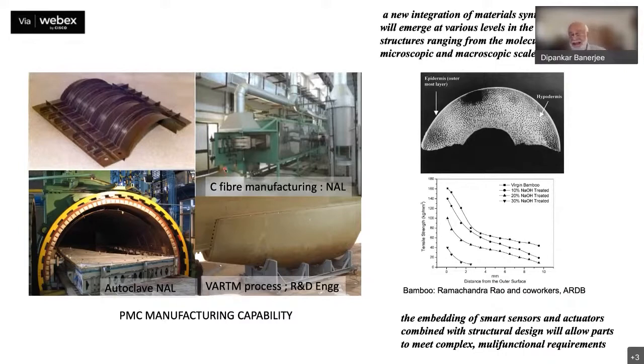And talking about composites at NAL, you all are so familiar with composite development and manufacturing as a part of NAL. But what I do want to point out is that there are opportunities for new integrations of material synthesis and design, because you can manipulate composite structure. You can architect the composite structure so as to obtain the precise kind of microstructure that you need for the local stresses that the material structure will experience. So, for example, bamboo has a higher density of fiber at its surfaces to withstand higher tensile stresses at the surface of the bamboo when it waves in the wind.